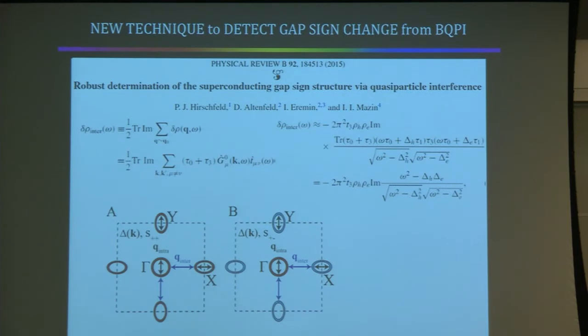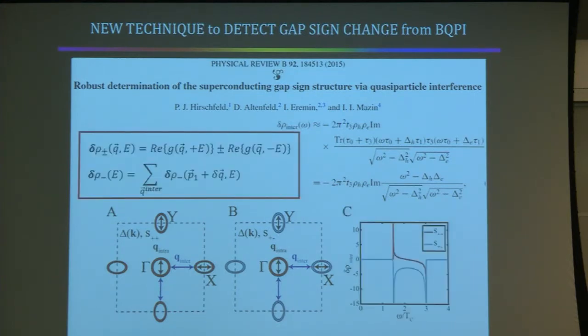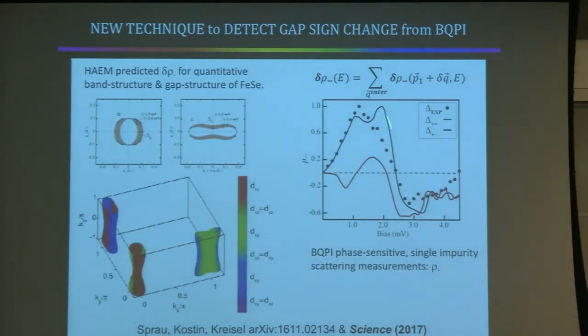Second thing we're able to do is measuring the sign difference between the gaps of a superconductor, which is hard to do. But these 4 guys, 3 of whom are quite renowned, Hirschfeld, Altenfeld, Eremin, and Mazin, found that interband scattering of potential impurities, simple impurities, has a term in it which has a product of the magnitude, not the magnitude, the signed value of the hole-like gap multiplied by the signed value of the electron-like gap. That predicts that you should be able to measure scattering interference between these 2 bands and determine from a model whether it changes sign or not. So we were able to implement that. I won't bore you with the results, but we can show very clearly that the 2 gaps I just showed you have opposite signs.